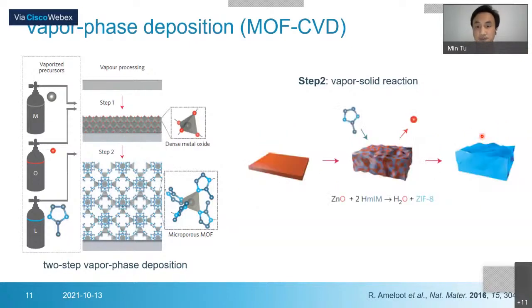And then the next step is the vapor-solid reaction. We do the deposition at a slightly higher temperature, around 110, 120 degrees, with the linker, in this case 2-methylimidazole. You can sublime it, and the vapor phase linker reacts with the zinc oxide, neutralizing it, and you have water out. By continuous growth, the linker can penetrate into the film and reach the bottom of the zinc oxide. Then you have the ZIF-8 film.